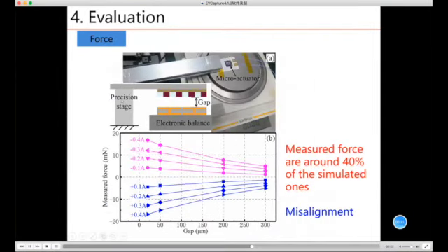Then, to measure the force generated between the mover and the stator, we use an electronic force balance. And this shows the measurement configuration. The mover is attached to a precision stage, and the gap is adjusted by the precision stage. By inputting different current into the stator, the force will be generated, and the force can be measured by the electronic balance. The measurement result is shown in this way.